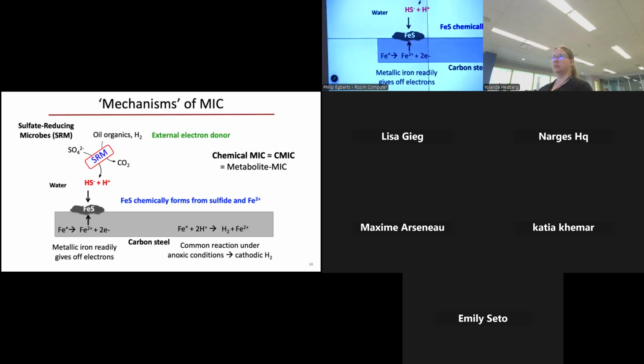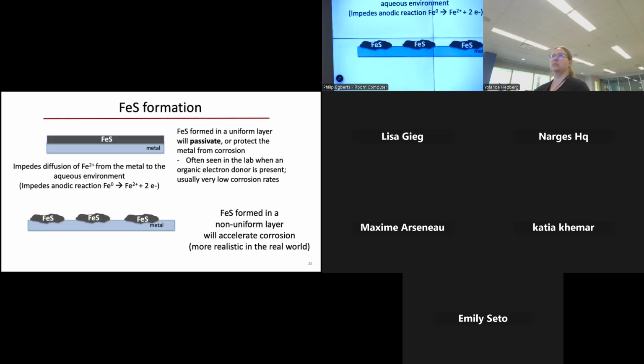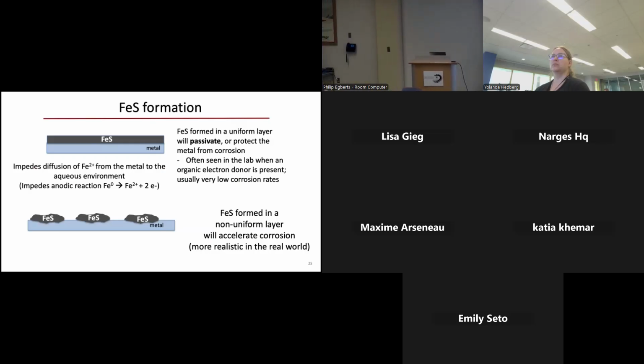So that iron sulfide chemically forms from sulfide and iron 2, okay? The reason that is a problem is that in the natural world, iron sulfide is usually formed in a non-uniform layer. It sets up a corrosion cell with the metal, and that will actually accelerate corrosion. So the fact that this product is generated because of the sulfide produced by those sulfate reducers, you can get a lot. It's quite an aggressive type of corrosion. But we also know that iron sulfide can passivate metal, so it can form a protective layer on the surface of that metal as well.